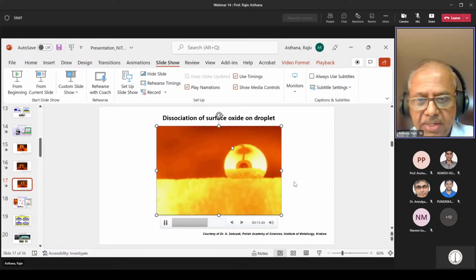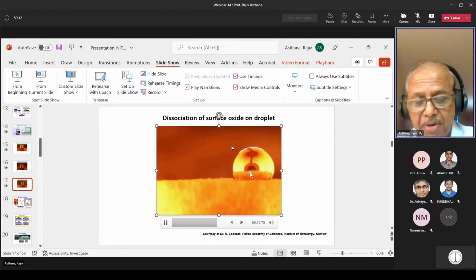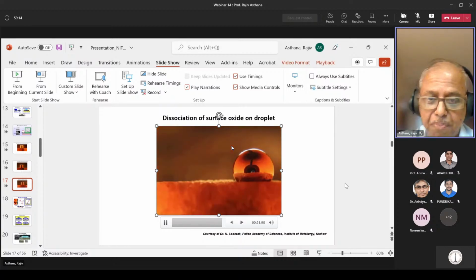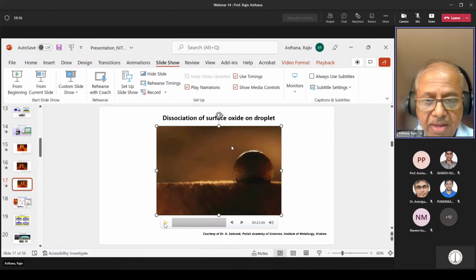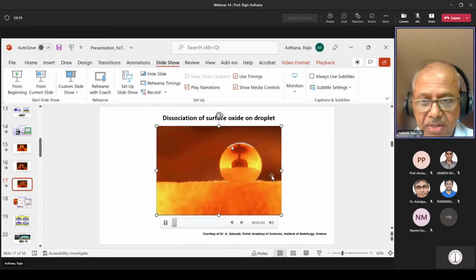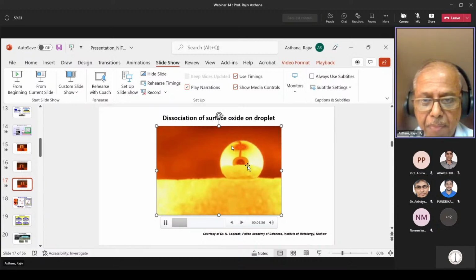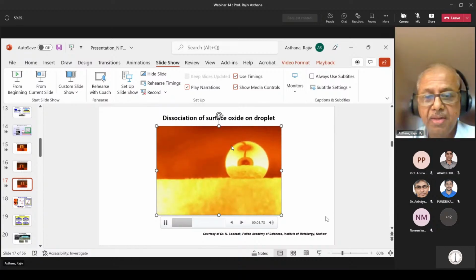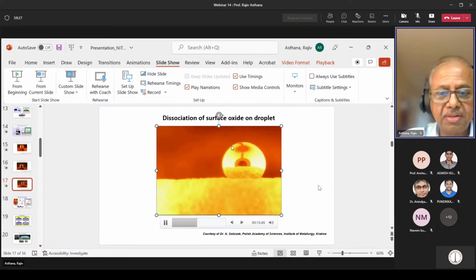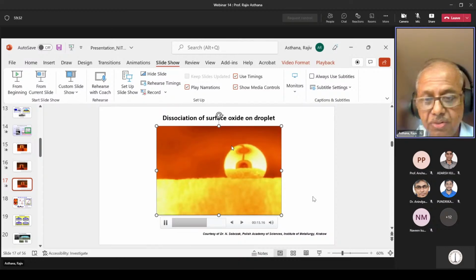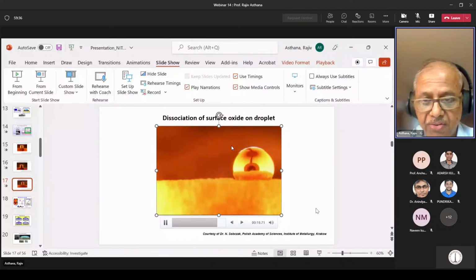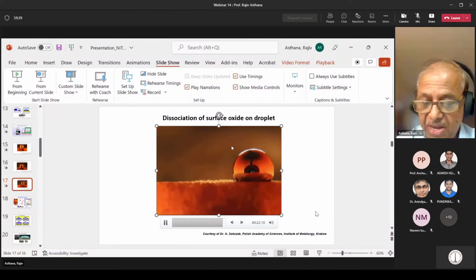And remember, all these experiments are being done under fairly high vacuum. Even then, the droplet is getting oxidized, which is not unexpected. And once again, if you take a look here, you will see the oxide breaking. You see here the little particles break, and it becomes a cleaner droplet. So these kind of experiments allow us to study the liquid metal solid ceramic interactions in more depth.